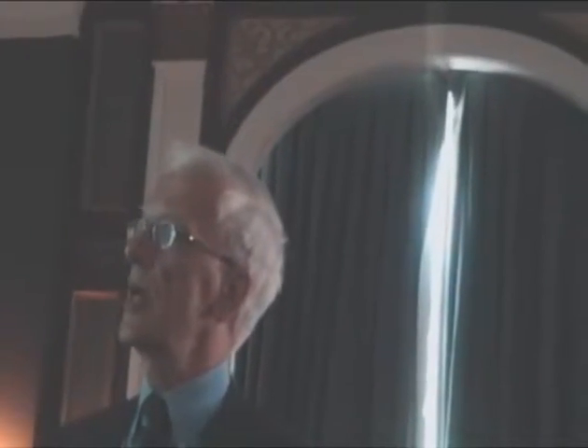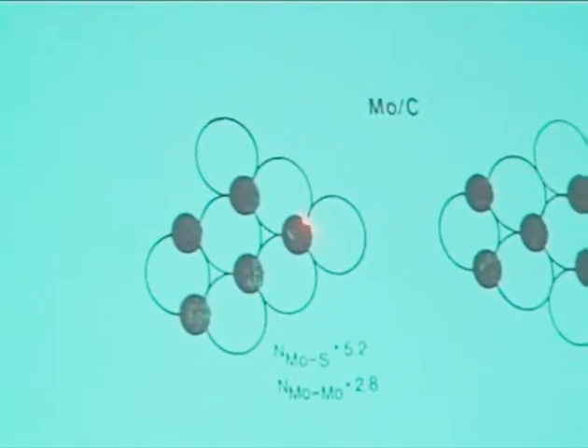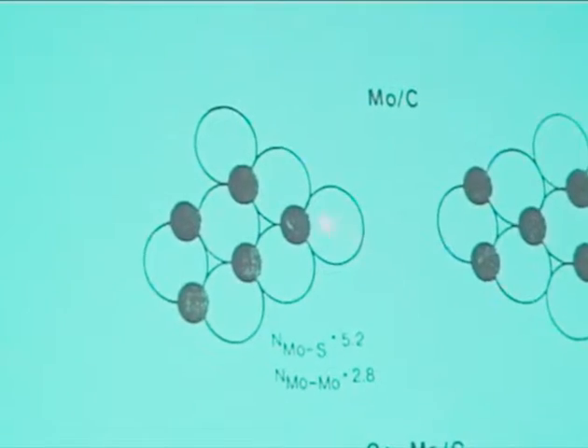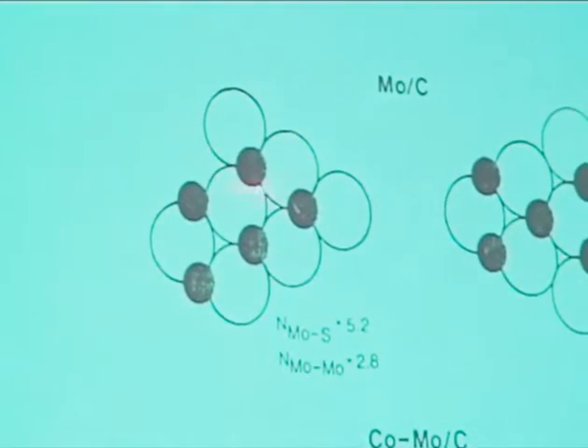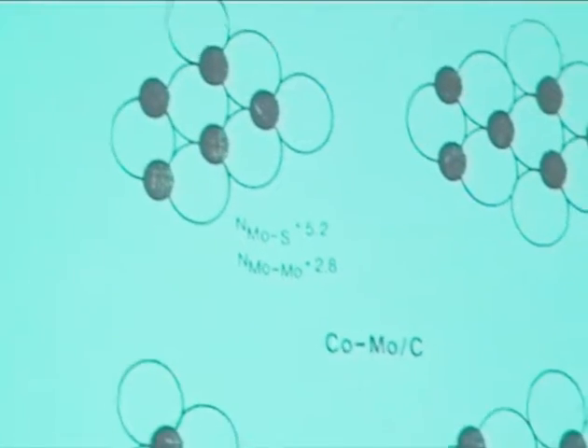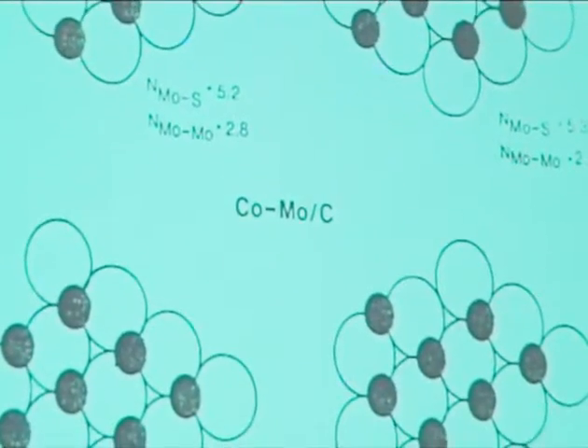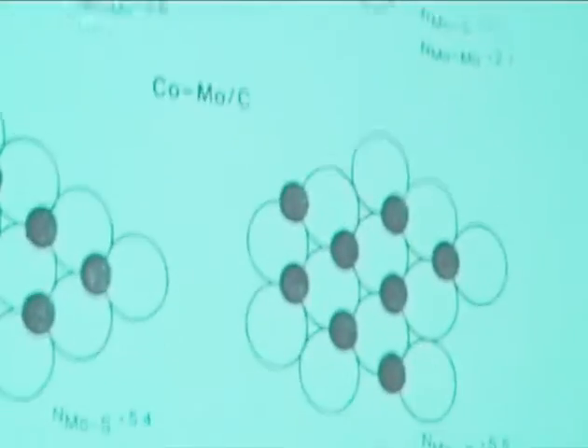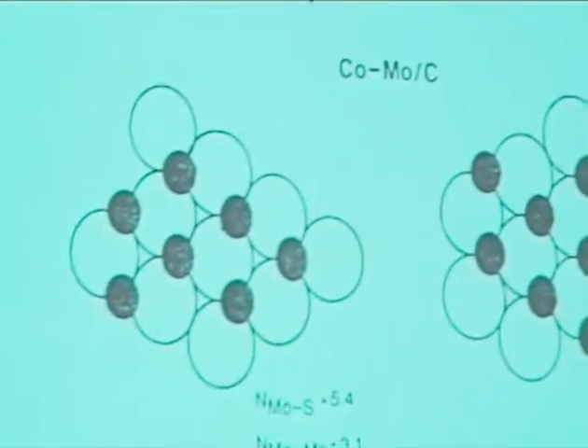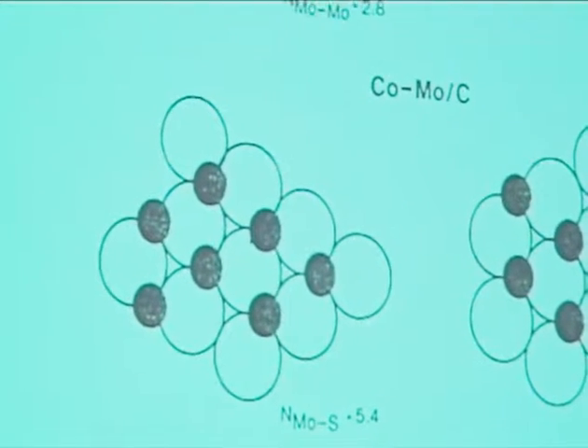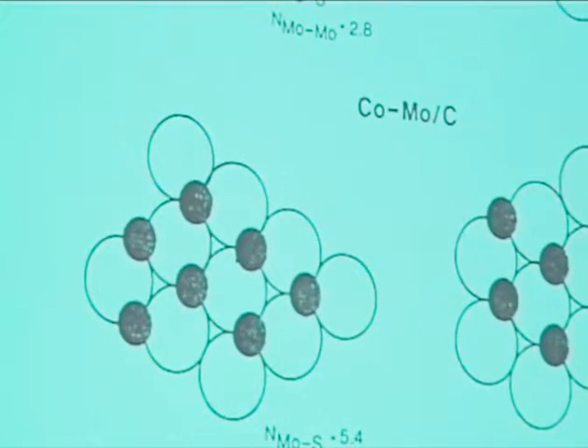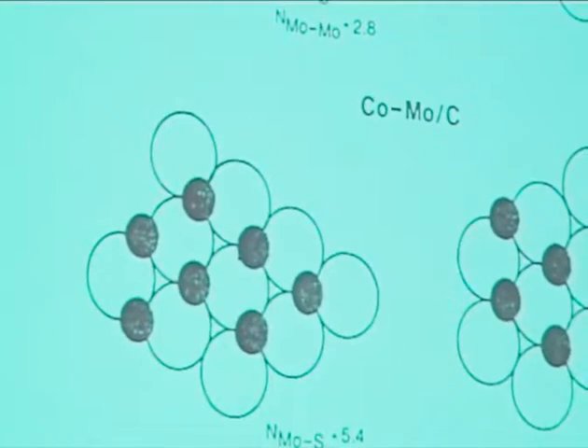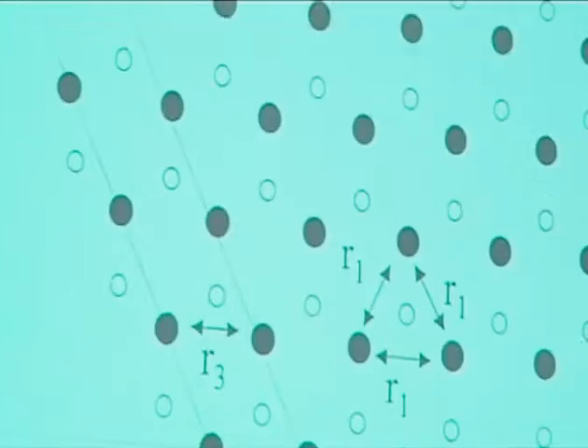And the other warning sign is that if you look at the forward scattering peak, which is from here to here to here and back, so from this to here and back, in these small particles there aren't too many of those passes. And still we saw the peak, suggesting that the particles were larger than we thought they were. So maybe there is something wrong with the EXAFS analysis. And yes, there is.